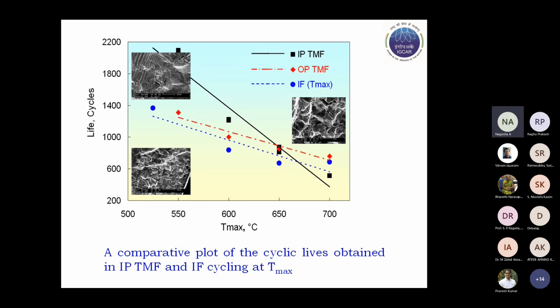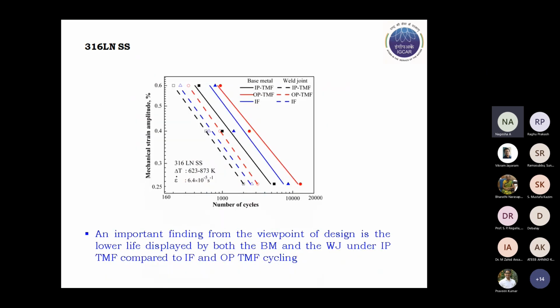Whereas when the temperature is lower, the tensile mean stress which is built up under OP TMF proved more damaging rather than the creep damage. And an important observation from the viewpoint of design is that the TMF gave rise to a lower life compared to the isothermal cyclic loading. So this signifies that the traditional approach is not a conservative design approach for these materials, and this situation is the case for both the base metal as well as the weld joint.